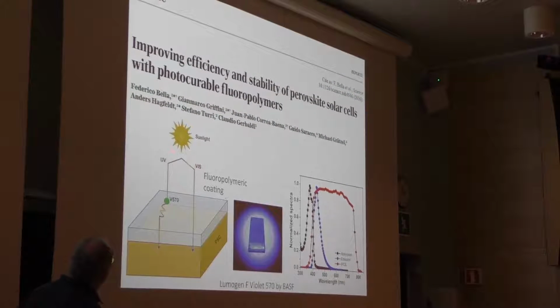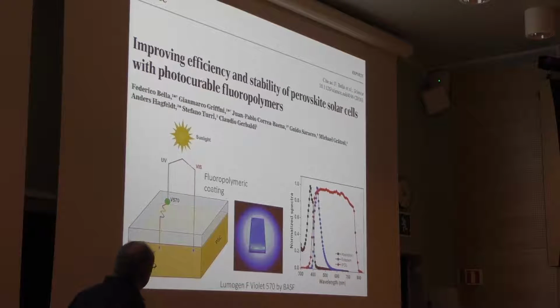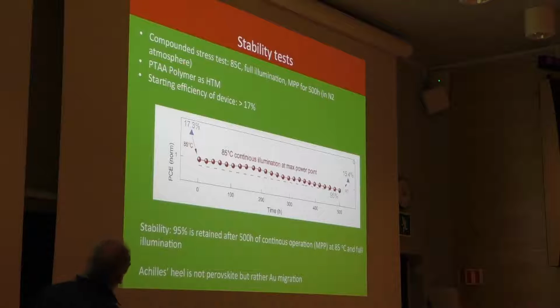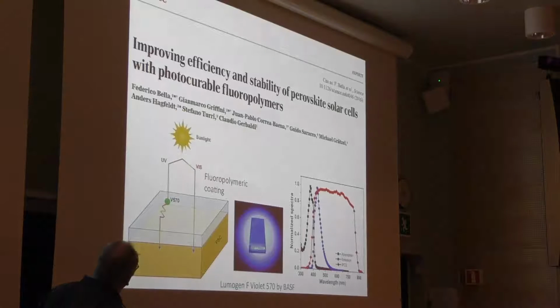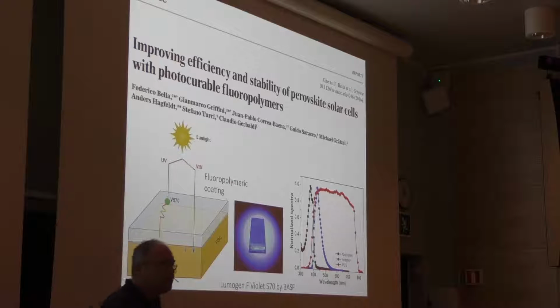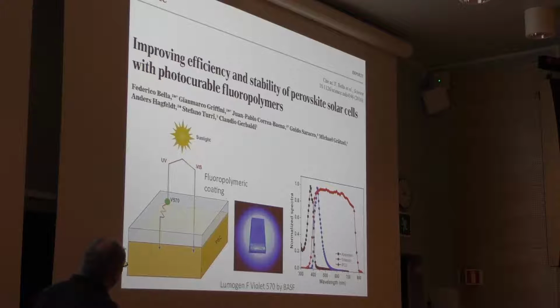We collaborated also with a group from Torino, Federico Bella in Italy, because in this work we are not good at sealing cells at EPFL, so this is under nitrogen atmosphere, so there's no sealing here. So what they did was to do sealing, and they sealed it with a fluoropolymer. They did two things: they sealed the cells, and on top of the top layer in the fluoropolymer they brought in some fluorescent dye molecules which convert UV light into visible light, because two problems here are UV light and of course humidity, water dissolves. So they solved two problems in this work. One was to solve the UV problem and even increase the current a little bit in the visible part here, and the other one was to avoid humidity.